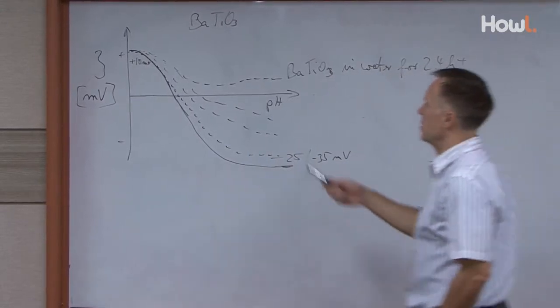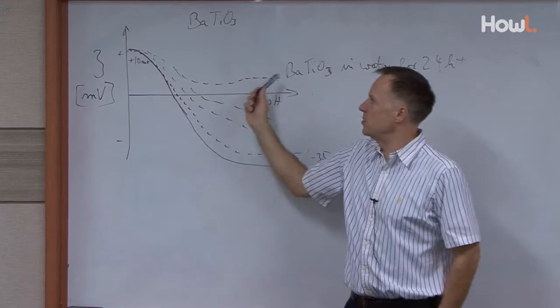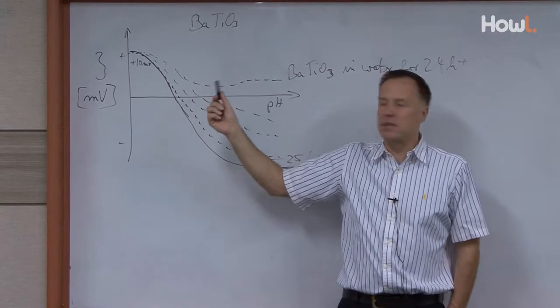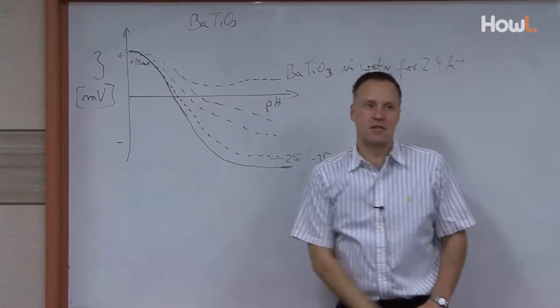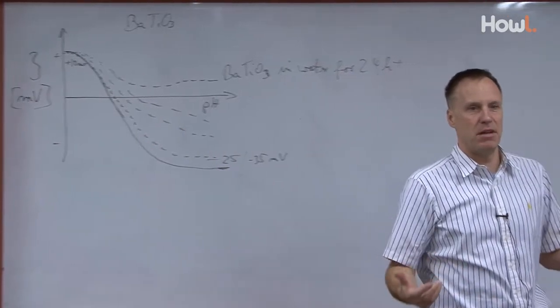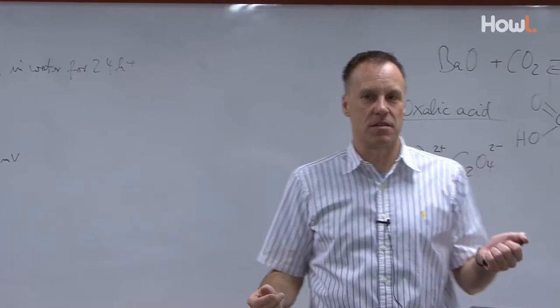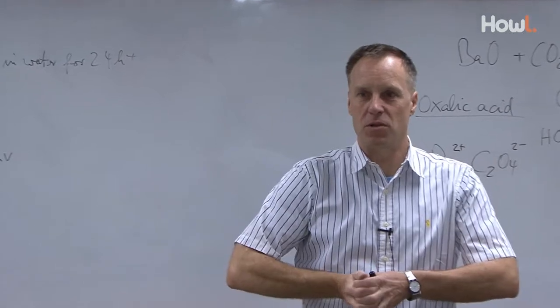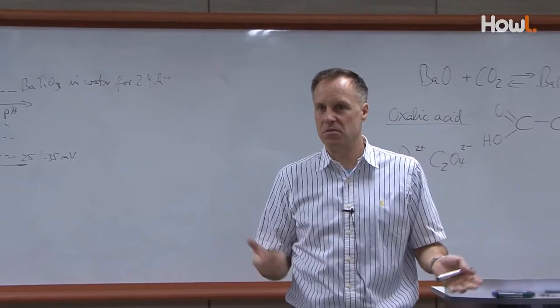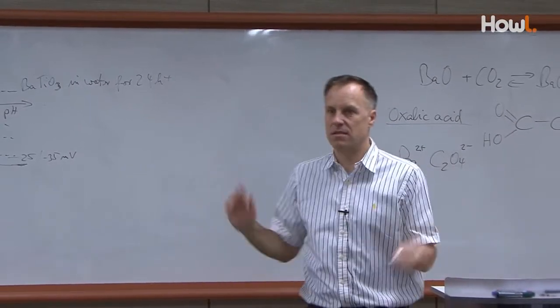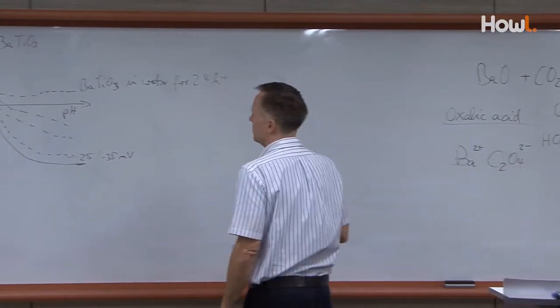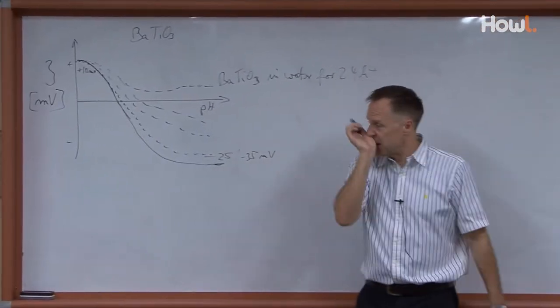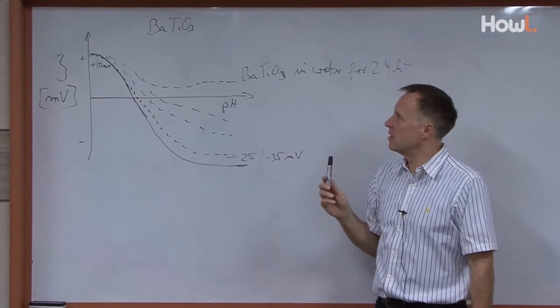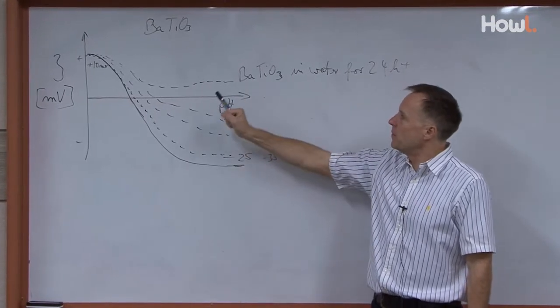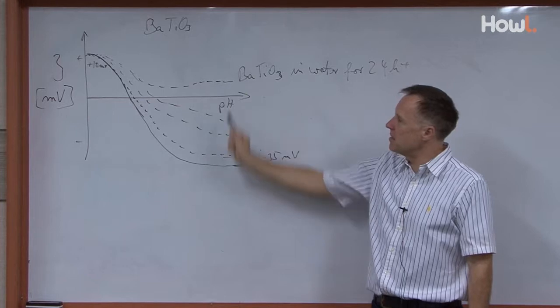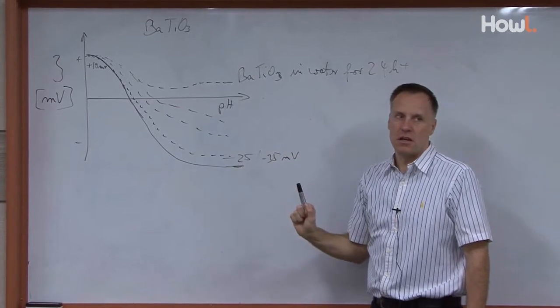And that also shows you this will be very difficult to process just with electric double layer stabilization, because the zeta potential is just 5 millivolts or 10 millivolts. And we didn't do this in the spreadsheet, but if you're below 20 millivolts, it's very difficult to disperse something. 10 millivolts is never enough. And especially barium titanate has a high Hamaker constant, so the van der Waals attraction is pretty strong. Yeah, so that's why barium titanate is a big challenge in the processing.